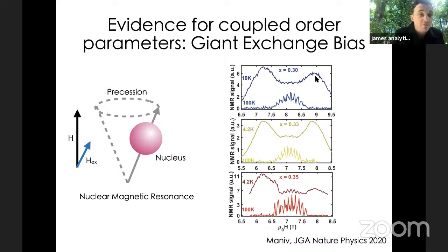So in other words, the defects are seeing the local environment of the exchange energy, the local environment of the antiferromagnet, and they see the same kind of environment as the antiferromagnetically ordered spins. So the defect spins see the same environment as the antiferromagnetically ordered spins.